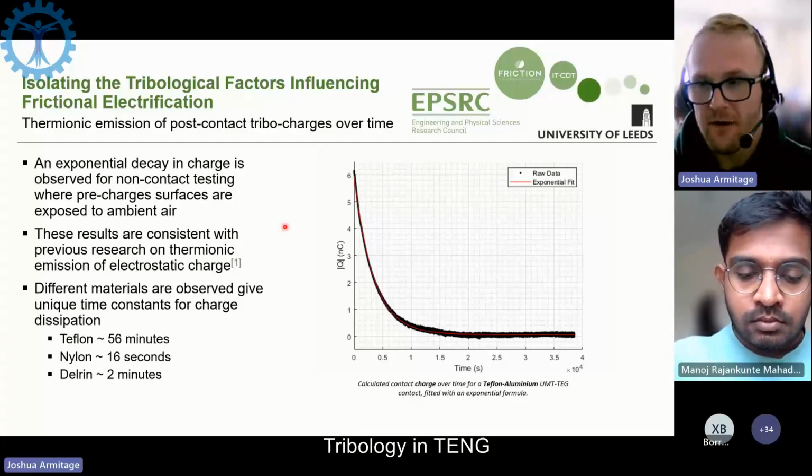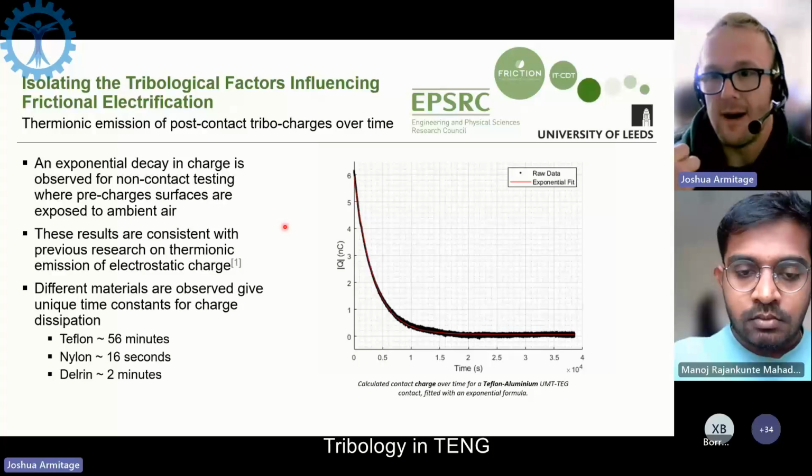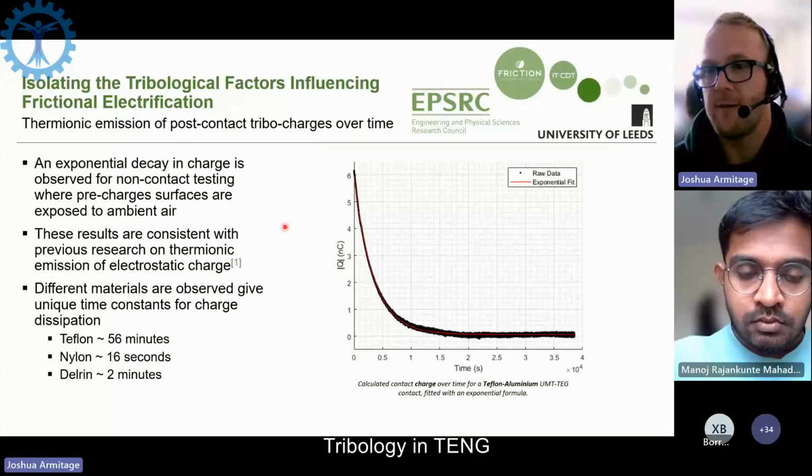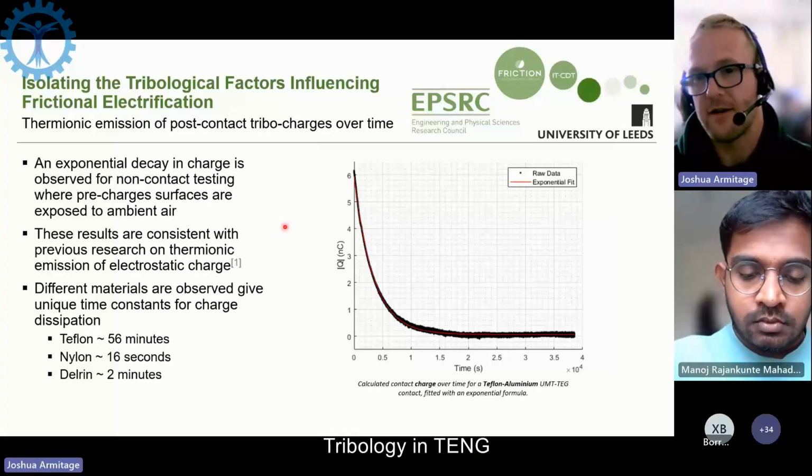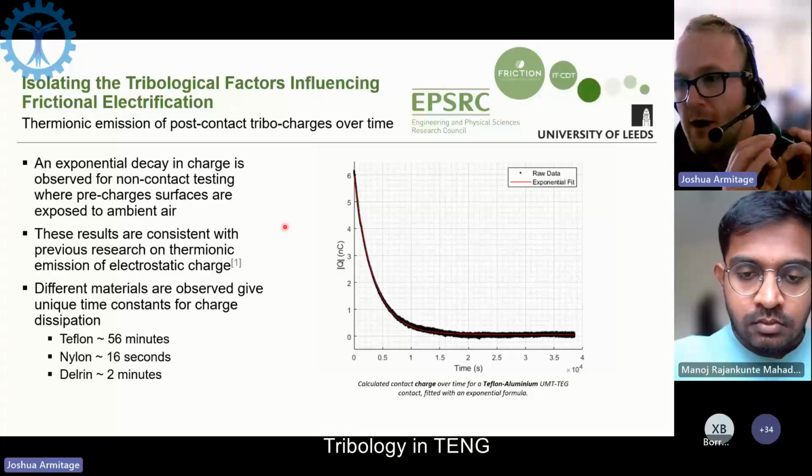So as we expose a charged surface to air, we have air molecules coming onto the surface, reacting, exchanging electrons, and ultimately dissipating that electrostatic charge. And we found that it is almost perfectly exponential in nature.